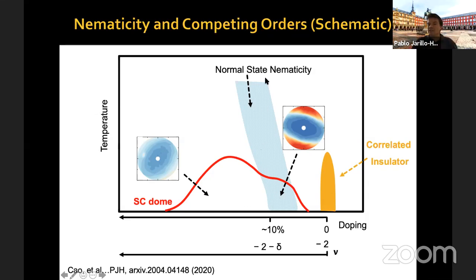So most likely this normal state nematicity is telling the superconductivity, now I want you to align in this direction, okay? So there is probably some correlation between the smooth rotation of the superconducting nematic axis in this region and the rather rapid reorientation of the axis here in this region, okay? So although we believe the nematicity might be of different origin in the superconducting dome and in the normal state, most likely this normal state nematicity has a strong effect in reorienting the superconducting order parameter in this narrow density range here, okay? And again, as I mentioned, you can see a lot more details in this publication, which is posted.